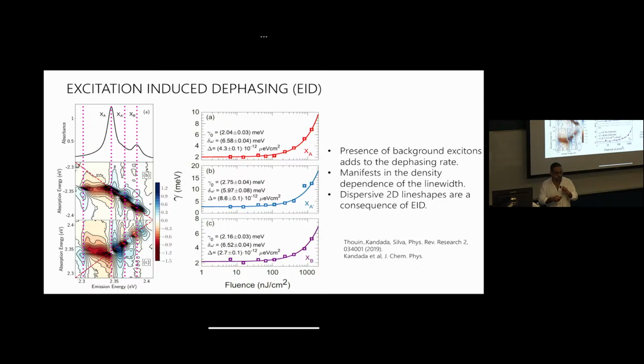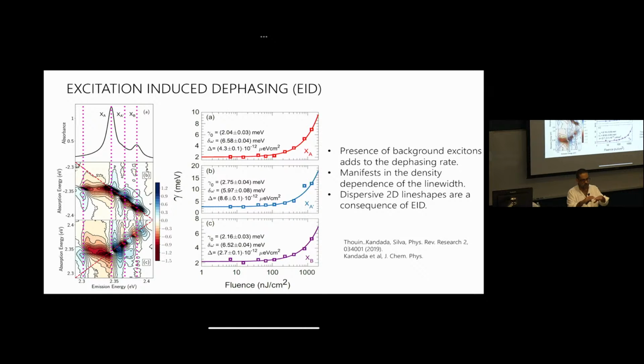But then when you increase the density, you also find that the density dependence is measurably different for XA and XB. Then this thing in between, which is XA prime, is a very mysterious thing to us at the moment. But you see that that's also very different. And so there's two things that I want to say. If you look at these deltas, if you measure the deltas for this sample, and then let's take another two-dimensional system that is also very interesting and relevant for the same applications that I talked about, but very different character. Let's say a transition metal dichalcogenide, which is just a fully covalent, single-layer, two-dimensional semiconductor.